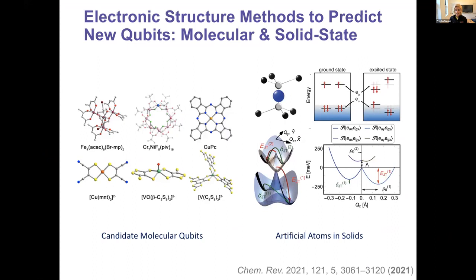On the right, I'm showing a problem that is a little more well established in the field, which is how do we think about these defects in solids that could act as optically addressable spin qubits. A good example of this is the NV center in diamond, but in addition to the NV center, there are group 4 quantum defects that have been recently reported, pioneering work, including by Natalie De Leon, in thinking about neutrally charged color centers, the silicon vacancy neutral in diamond, but there's a whole host of these. And something that we highlight is that the correlated nature of the electronic and nuclear degrees of freedom that show up in some of these cases, particularly the Jahn-Teller effect in these systems, is incredibly challenging for conventional theoretical techniques.